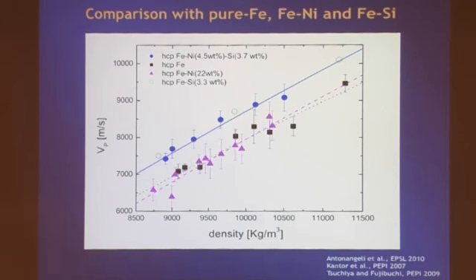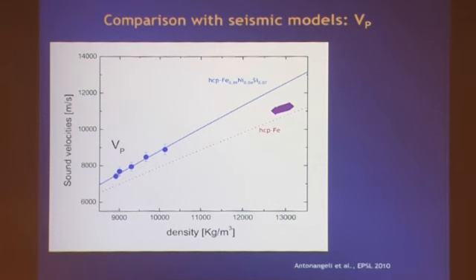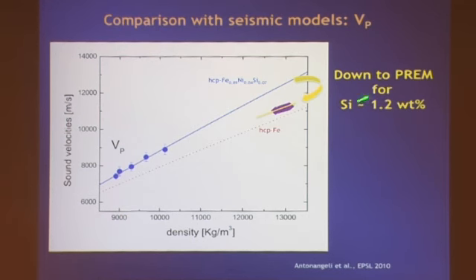So now we can see what happens if we extrapolate this trend to the density of the core. And here are the results. This is the PREM model, and as originally suggested by Fiquet and co-workers, pure iron extrapolates lower than PREM. Adding 3.7 weight% of silicon makes it too fast. But this time we have two data sets that bracket the velocity of the PREM. So we can play with a linear mixing model, and we end up with values straddling the PREM for a silicon content of about 1.2 weight%.